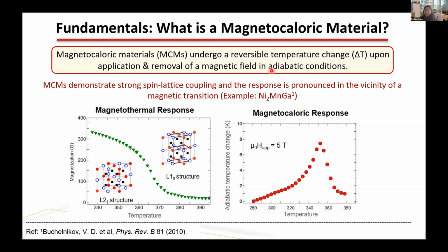To explain this, let's look at a prototypical magnetocaloric material, a nickel-manganese-gallium Heusler alloy. This alloy at room temperature shows an L21 crystal structure, such as that shown here. It is ferromagnetic at room temperature. Upon heating, it undergoes a Curie transition - a ferromagnetic to paramagnetic transition - at around 360 Kelvin. This magnetic transition is accompanied by a simultaneous crystal structure change from an L21 to an L10 crystal structure, so it's concurrent.